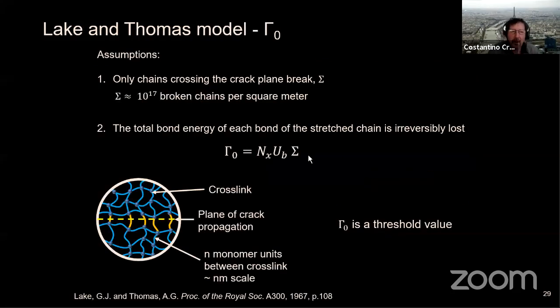So this comes back to the Lake and Thomas model. There are not that many molecular fracture models, and an old model is that by Lake and Thomas, who pointed out that in threshold conditions, meaning if you completely forget about viscoelastic dissipation, the minimum energy needed to break a network is this value gamma zero, which is the number of chains crossing the plane of crack propagation.